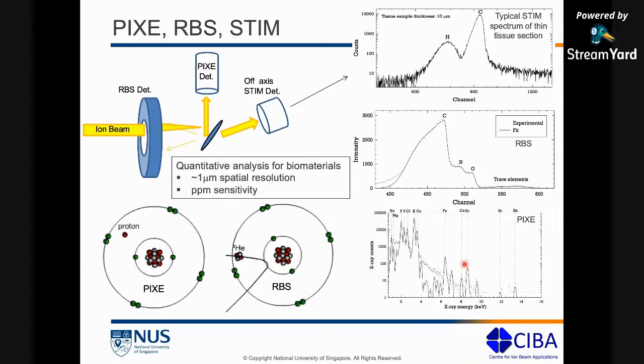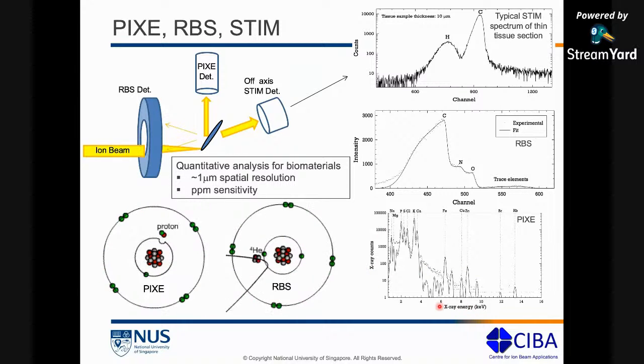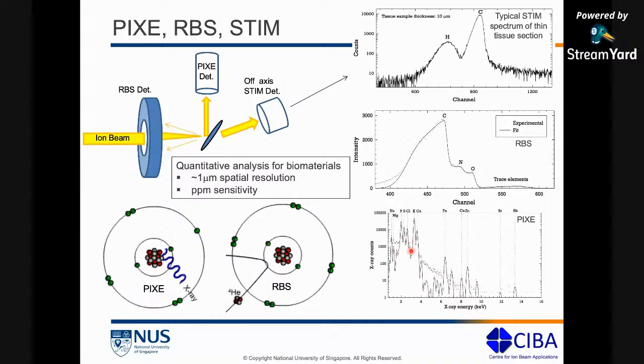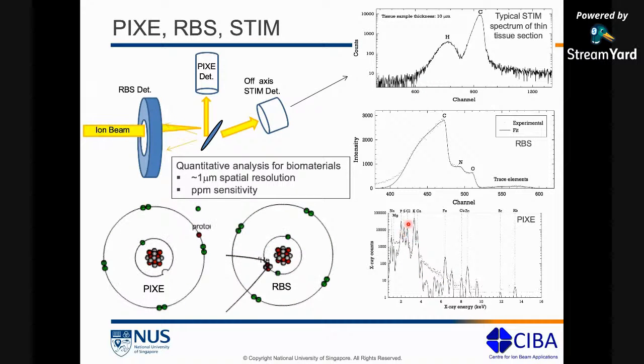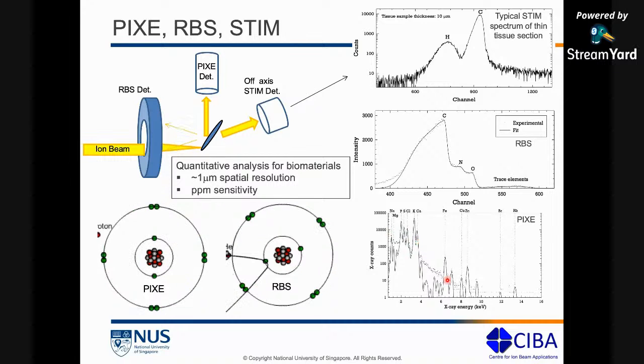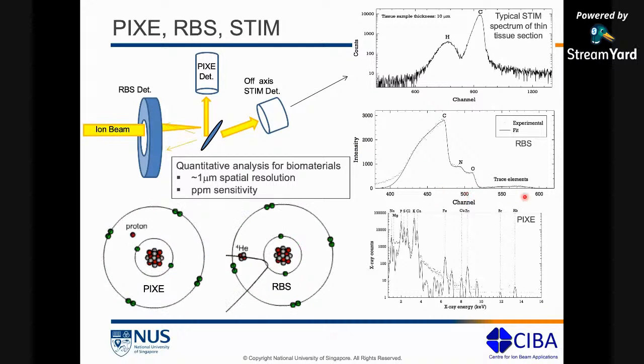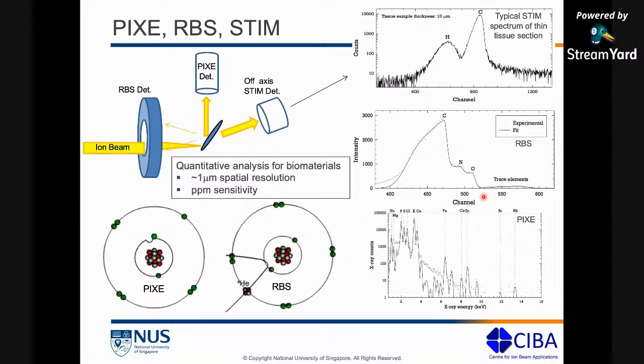So let's see what the PIXE signal looks like. So we have an X-ray count on the Y scale, and then X-ray energy on the X scale. And then we have these X-ray peaks from the different elements that are present in your sample. And once we calibrate the spectrum, we can then identify which peaks and which elements are present in your sample. The RBS is similar. We have the intensity or counts on your Y scale, and then we have the channel number. So this channel number is the electronic channel coming from the data acquisition. But once calibrated, we can convert this channel number to an energy scale.